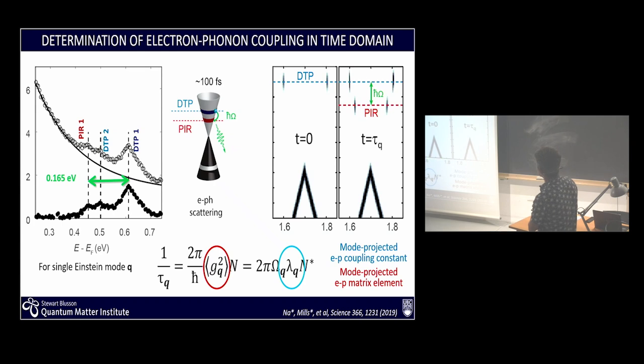So experimentally, this is shown here. Instead of the angle resolved map, I'm showing an angle integrated spectrum of a feature like this. And here you see the actual raw data. You see there is a background. This is the electron-electron scattering. But on top of the background, there is some structure. If we subtract the background, the structure is 3 peaks in this case. 2 of them are optically allowed transitions, so these are really transitions between valence and conduction bands. But then there is a feature which is not an optically allowed transition. It's separated in energy exactly by the energy of a q phonon for the system.